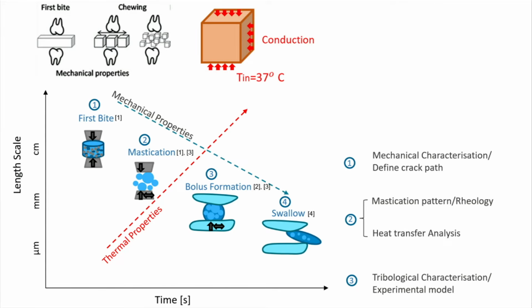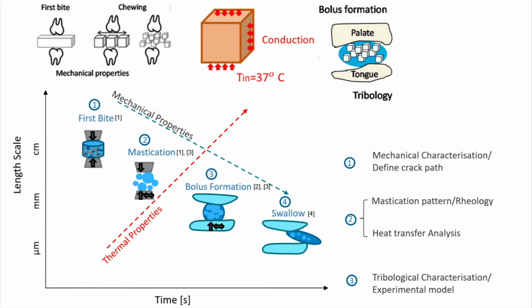Once these particles are formed, they mix with saliva and are squashed against surfaces in your mouth to form a bolus, as it's called, a soft solid. And then you would do the rheological test to characterize it. Of course, this interaction with the tongue and the top of your mouth is also quite important, and maybe it does affect consumer perception as well.